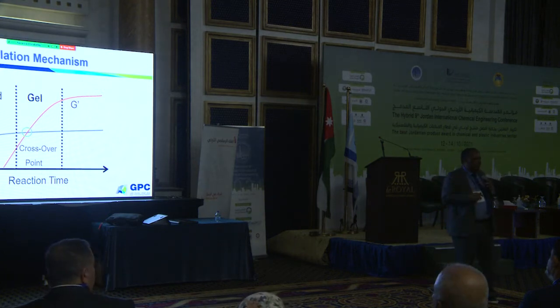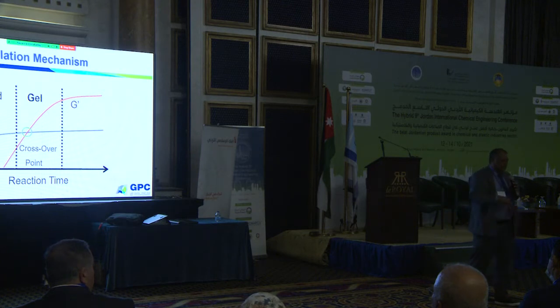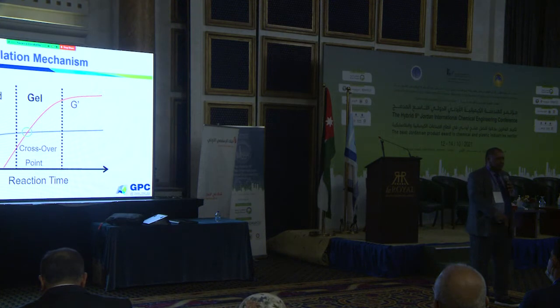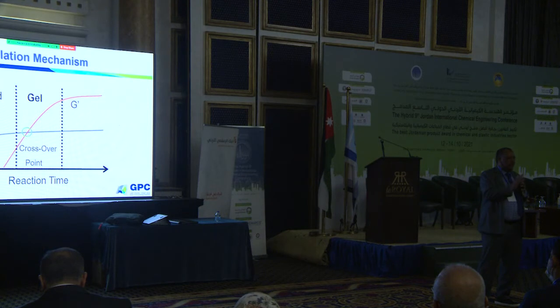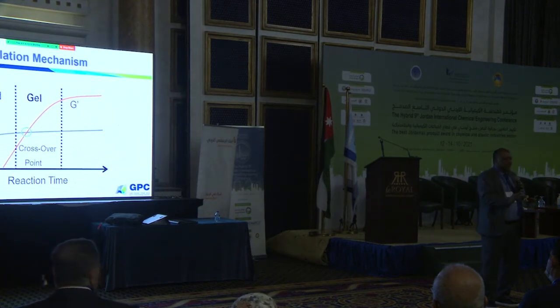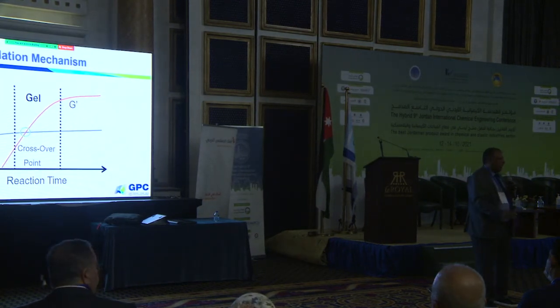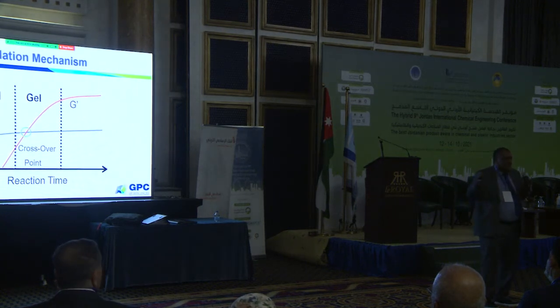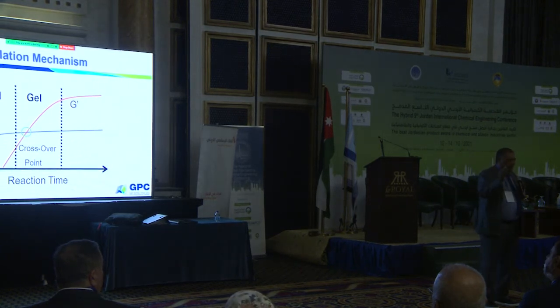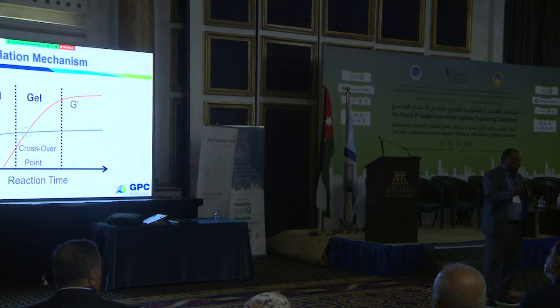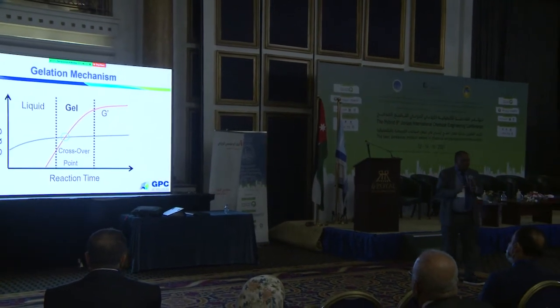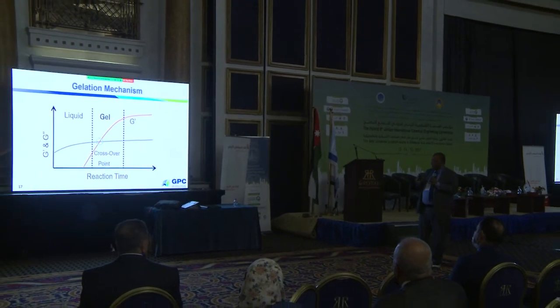Why should we worry about this? When we inject these materials, they have to go through a long tube, and in this tubing we don't want any gel to form, otherwise it will block. So you have to know the kinetics of gelation very well, so that by the time you reach the target zone, you still have a liquid. Then you isolate the zone, and the temperature of the reservoir will set the gelation temperature. We don't want formation of the gel anywhere else along the 1,000 or 2,000 meters before the target zone. So you have to be very careful about understanding the chemistry and the gelation mechanism.